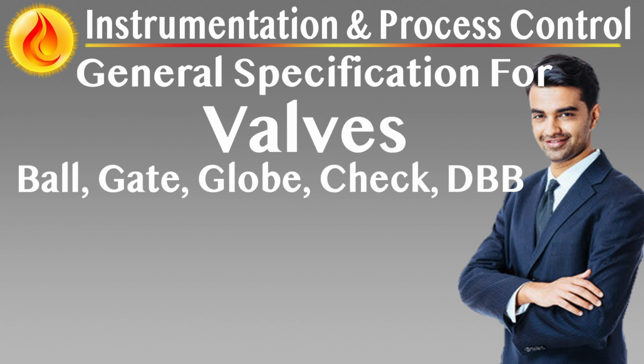Materials of construction for DBB valves must be suitable for the process media, including sour, abrasive, or corrosive fluids. Carbon steel bodies may be accepted where permitted, but must include CRA weld overlays, e.g. Inconel 625 or UNS N06625, on all wetted and sealing surfaces. For sour service, all wetted parts must comply with NACE MR0175/ISO 15156. Non-metallic seals must be resistant to explosive decompression and chemical attack, and test data for O-rings, lip seals, or seats shall be submitted for review.